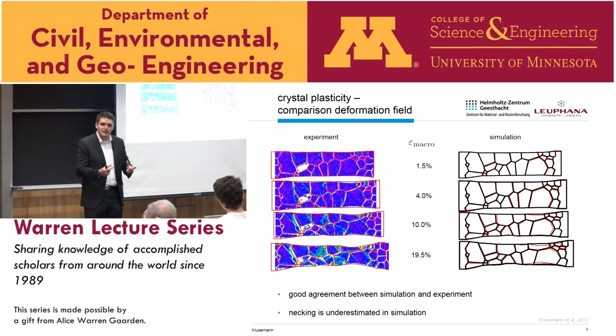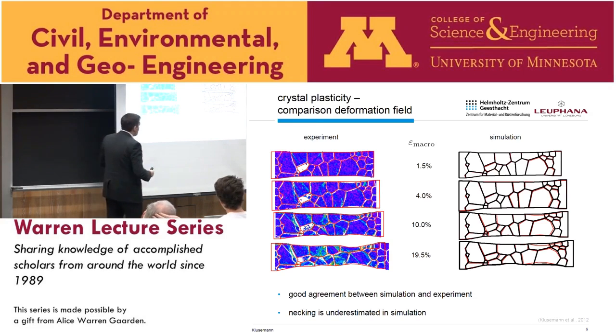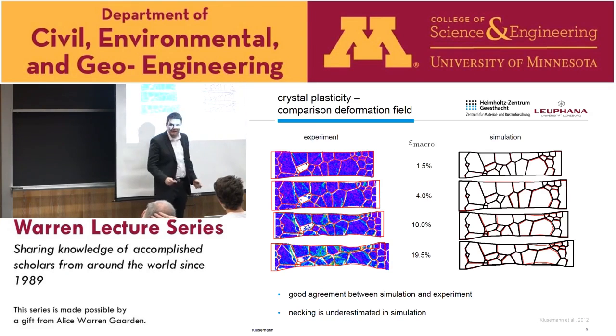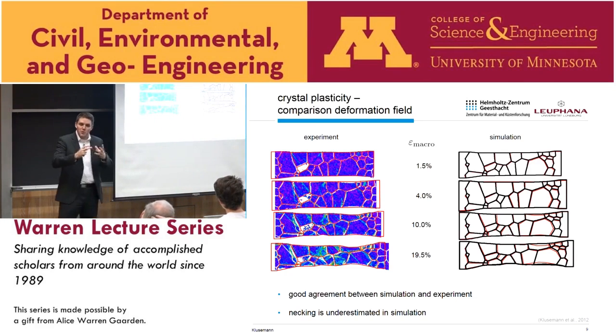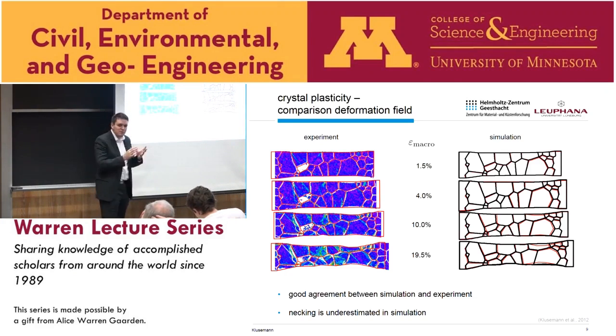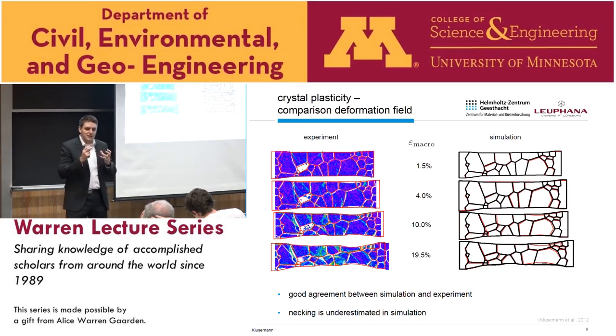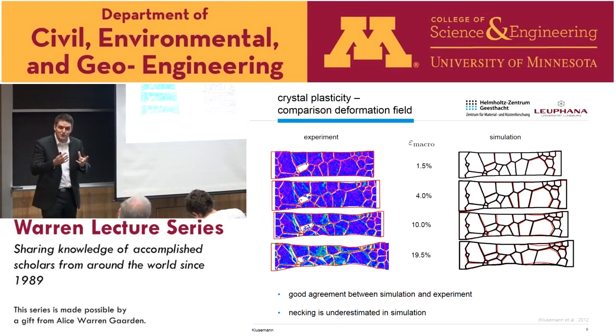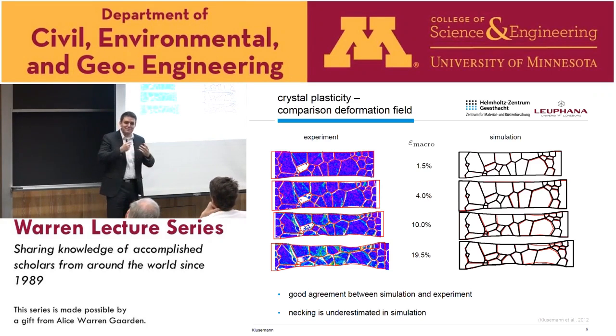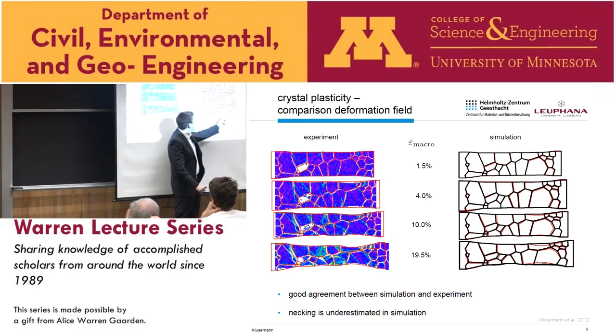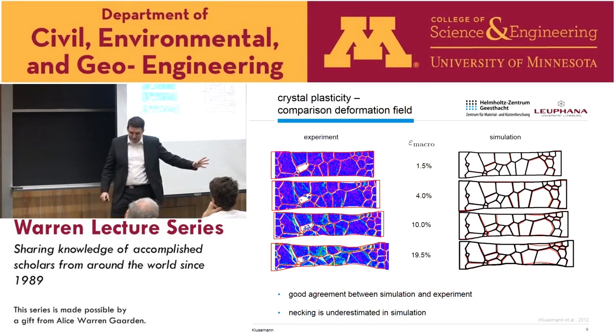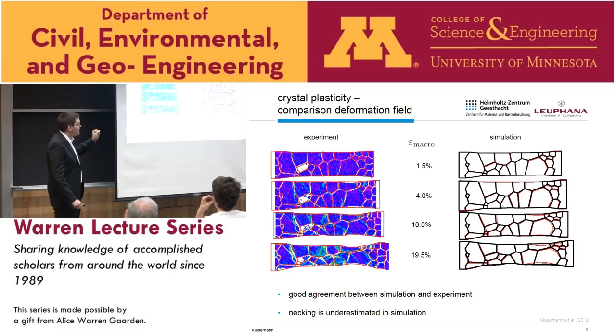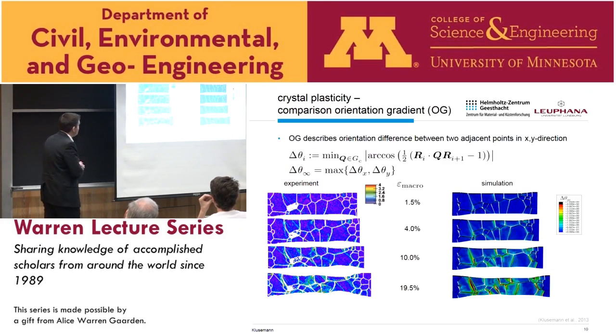It's just a single crystal model which is identified on material data, applied to the oligocrystal, but there's no identification process. This was with our partners, in particular the University of Saarland, where Horst Wehoff did the experiments. They were really surprised that we could predict this quite accurately without any specific identification. And this shows that a simple crystal plasticity model is very accurate in predicting the deformation, which was very interesting to see for this kind of material. However, as mechanicists, we were still interested in seeing why. Why is this showing this deviation? And this is a quantitative comparison, but only with respect to the deformation field. We had more information from the experiment, so let's go one step further.